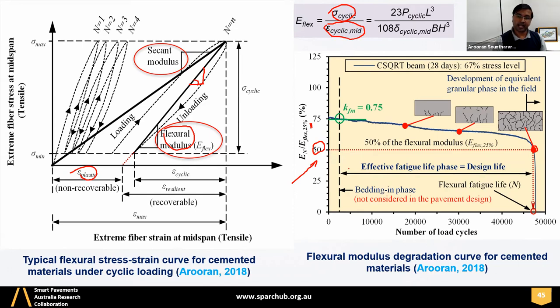Right? That means the effective fatigue life here is marked as the number of load cycles required to reduce the modulus of the pavement from initial value to its 50%. That is commonly referred to as the flexural fatigue life of the pavement. Right? Then based on this definition, what we do is we change this sigma max in the laboratory, in the four-point bending. Sigma max is changed in order to capture the number of load cycles at that stress level. And then we develop the stress-strain relationship, which is so-called the fatigue curve, right?